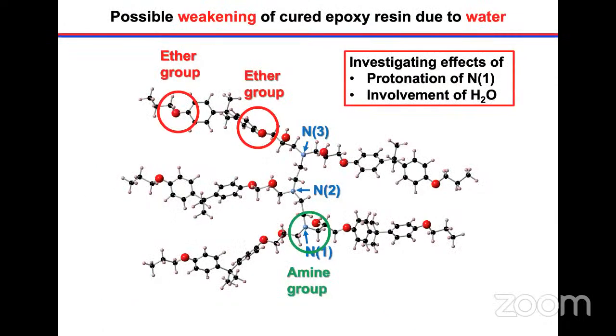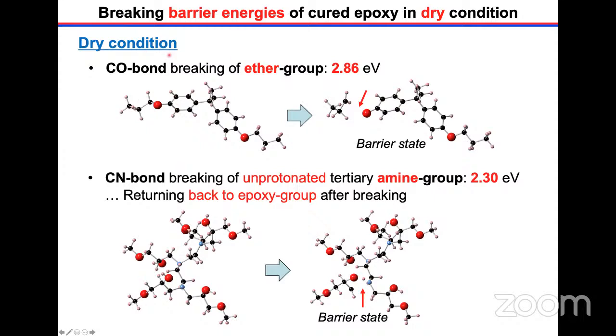So let's think about the possibility of weakening of the chemical bond by the existence of protonation and the existence of the H2O molecule. Then I'm trying to talk about this amine group reaction and also this ether group reaction in the existence of the two effects. So in the dry condition, we have no water here. In this case, this is the reference data. The CO bond breaking barrier energy is 2.86 electron volt. This is the barrier energy state, breaking this here.